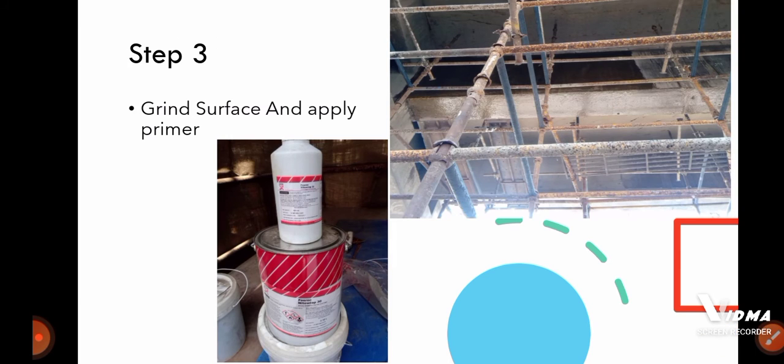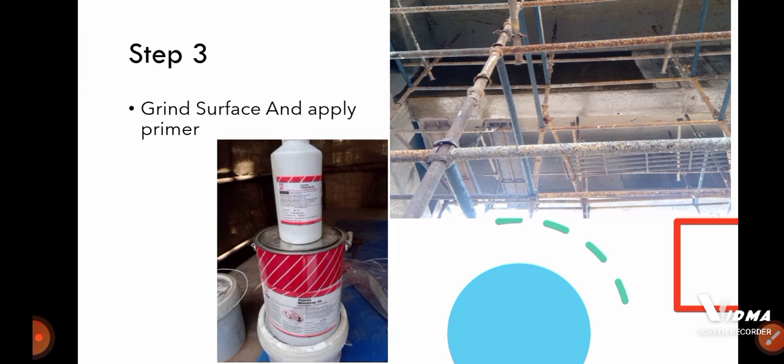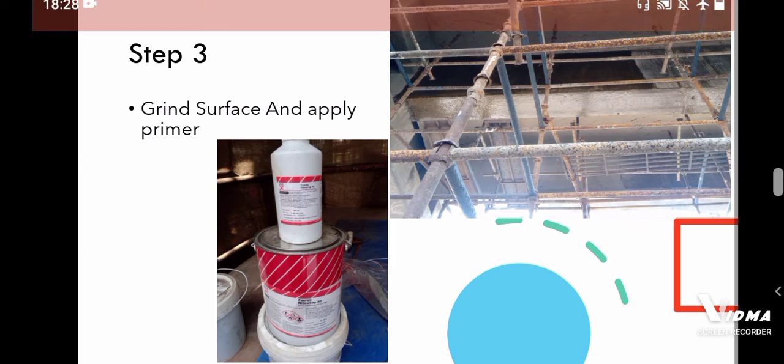Now this is time to apply your FRP, but before applying your FRP, what you have to do is prepare the surface by grinding it for smooth surface. Not only that, the FRP cannot be attached with your concrete directly because the compatibility is completely different. There is no compatibility between your concrete and FRP. That's why in between them you need to provide some adhesive, but before applying the adhesive you need to apply a primer. Here you can see I am using primer - this is the primer Fosroc and the name is Nitoprime 30. This is the primer I have applied, that's why the surface becomes shiny.